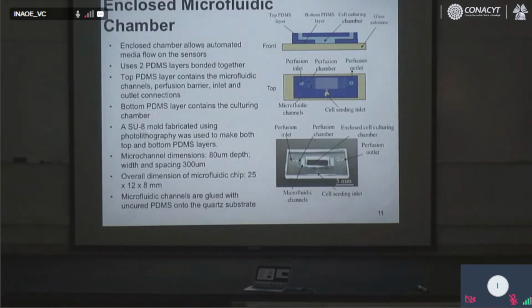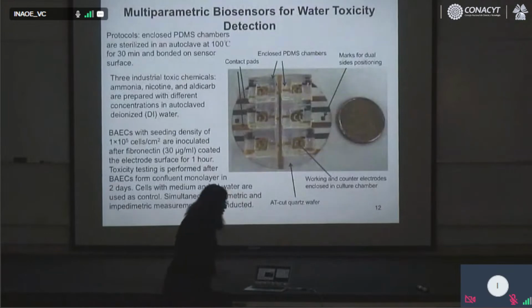And we use PDMS, and we use SU8, and we use 2 layers. We fabricate 1 layer of PDMS, which contains only these cell culturing chambers. And then the second layer contains this structure of the microfluidic channels. And we put this on top of our chip. This, what you see here, are the cell culturing chambers on the fabricated chip before connecting the chip to the printed circuit board.